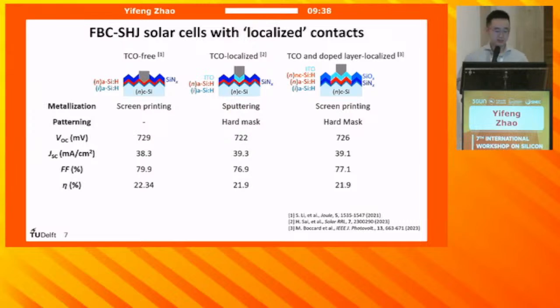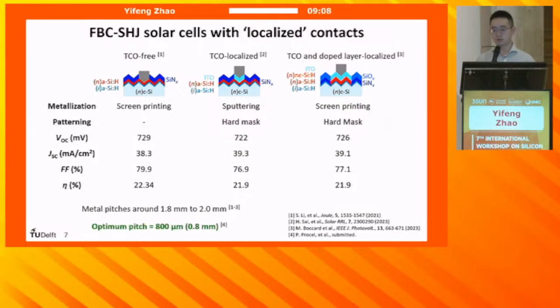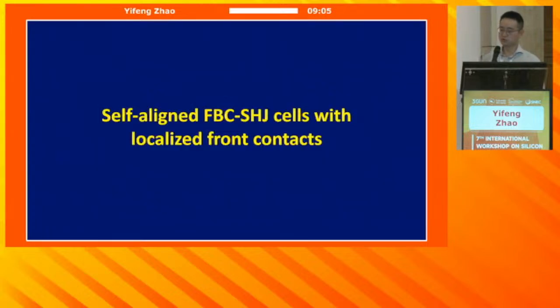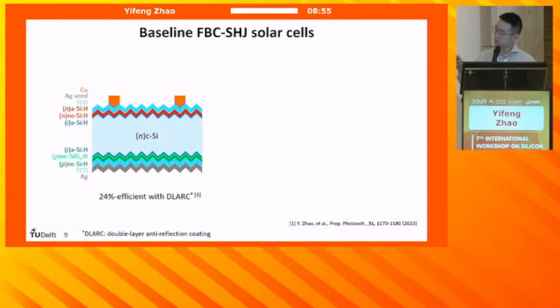And among those studies, the localization patterning was realized by deposition through hard mask, which often requires careful optimization of deposition conditions through the mask, and also requires careful alignment of those hard masks. And furthermore, those metallization techniques realized either by sputtering through hard mask or screen printing often feature a pitch size around 1.8 millimeter to around 2.0 millimeter. And according to our simulation before, the optimum pitch is 0.8 millimeter. So to address this issue, here we introduce a self-aligned front-back contacted silicon junction solar cells with localized front contacts, a process to develop that.